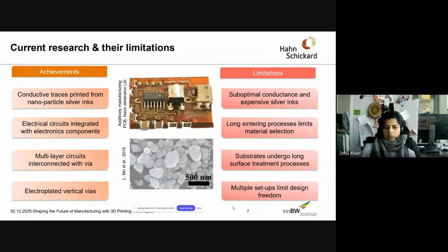And this is because, as I show here in the photo, this ink is made of nanoparticles, and these are not able to fuse to the level that we would want to get the good conductance that the material inherently presents. Because we are limited by the dielectric substrate, these polymers cannot go to the temperature that the conductive inks usually require for sintering. Nevertheless, to even bring it to the conductive state, we need long hours of sintering processes, and this is another limitation.